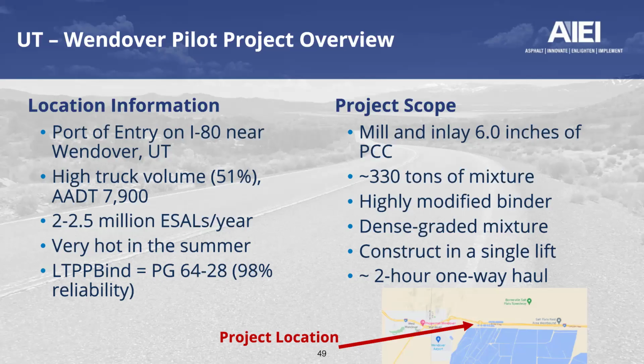At this port of entry, the DOT had seen notable struggles to keep material, both asphalt and concrete, long term. Admittedly, the concrete was giving them more years of life than the previous asphalt mixtures, but they were hopeful that this mixture might give them superior performance. I say that they were hopeful, but the individual who selected this had a significant amount of money within the budget because he anticipated that it would not perform. He thought that the incredible truck traffic that they have there would prove to be too much for this mix.